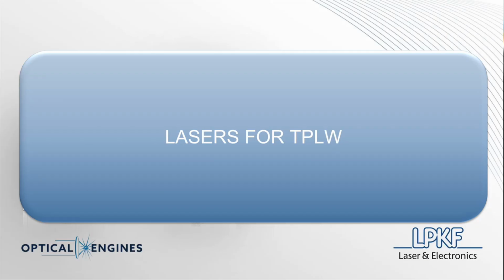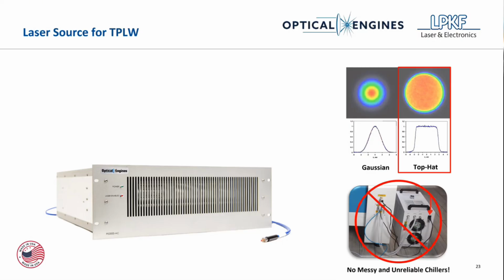All right, I'm going to jump into lasers for this specific 2 micron welding. Optical Engines has pretty much the only source that I've found on the market with a top hat beam profile, okay? So if you look at the illustration here, traditional lasers, fiber lasers, single mode lasers are Gaussian in profile. Through Optical Engines' special beam shaping technology inside the box, they're able to get a top hat profile, which makes it much, much easier, like I mentioned earlier, to not get any burns, because otherwise focusing that laser energy so precisely at one spot tends to burn before it's actually going to propagate that heat down into the parts. So a very important key feature.